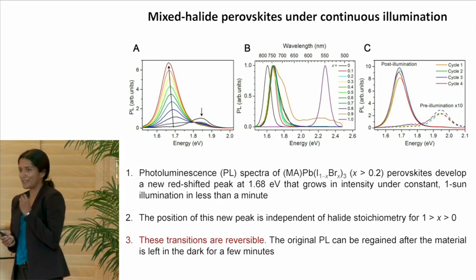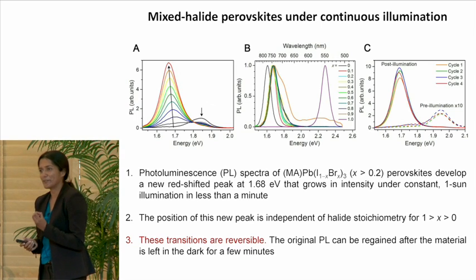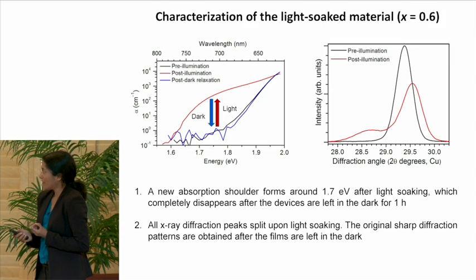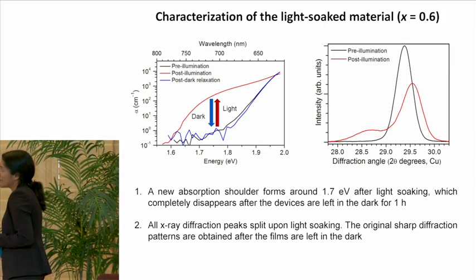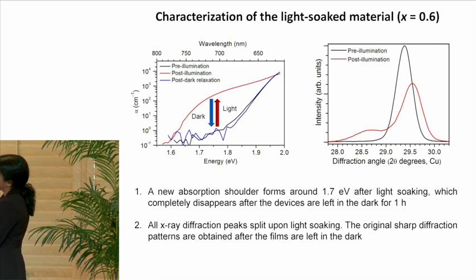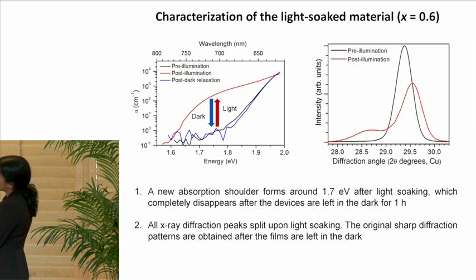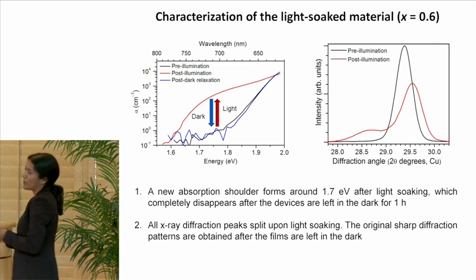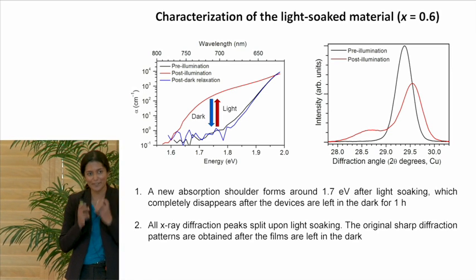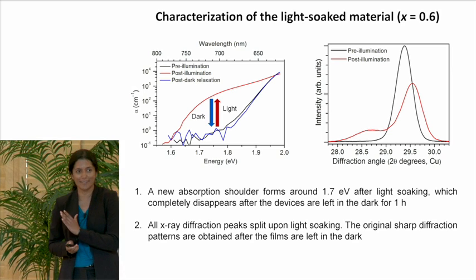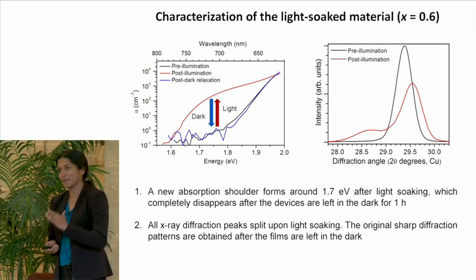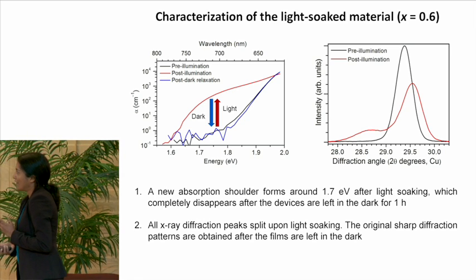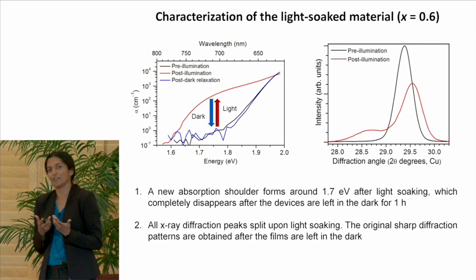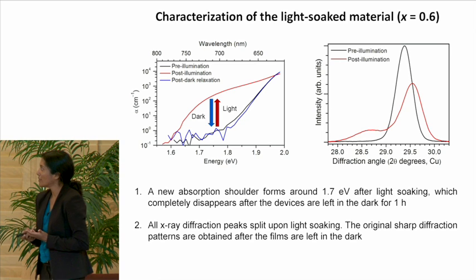So we decided to study this material under illumination to figure out what on earth was going on. And we did several experiments. So here, Eric sees that under illumination, a new sub-band gap shoulder grows in at around 1.7 eV. And again, when the light is turned off, the shoulder decreases. Light is turned on, the shoulder grows in, and so on. This can be cycled.